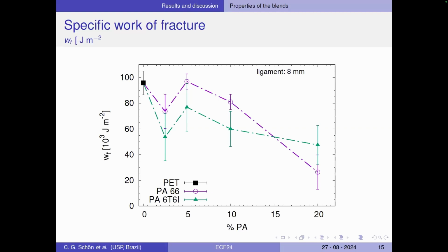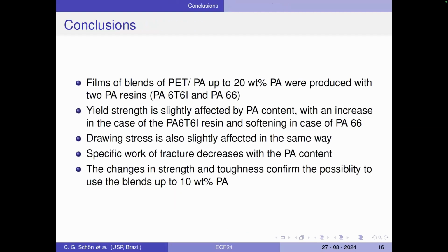In the work of fracture, then we see an effect, and of course, if we mix too much PA, we pay with toughness. And finally, these are the conclusions. So we could produce the films. So there is almost no effect in the yield strength. There is also no big effect in drawing stress. The specific work of fracture decreased with the increase of PA, of course.